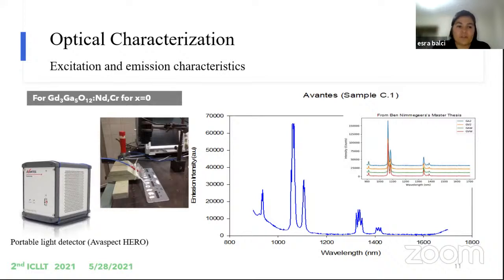Our Avaspect Hero is a portable light detector, as I said. The excitation was performed using 500 milliwatts and an 808 nanometer laser. The wavelength range is actually limited from 900 nanometers to 1700 nanometers. Actually, taking measurements is very easy.